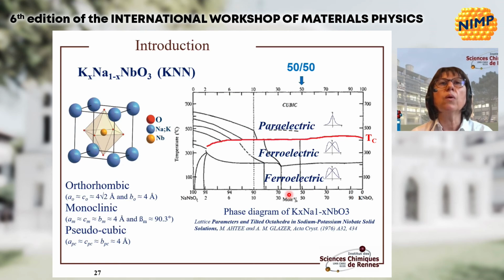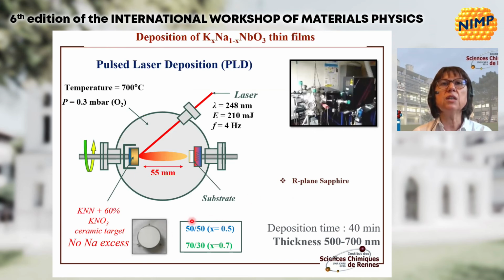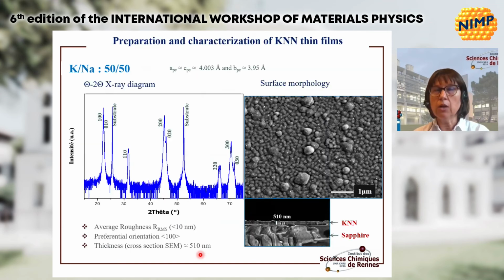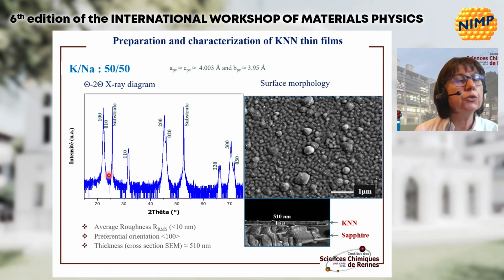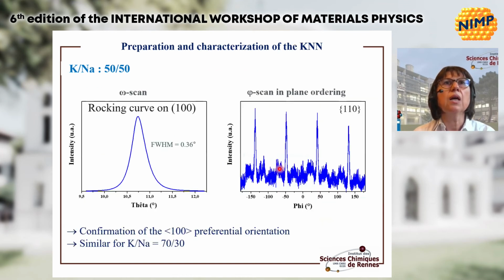So, we have already seen the phase diagram. The main composition we have studied is a 50-50 ratio between potassium and sodium, but we have also compared it to 70-30. Thin films have been deposited on R-plane sapphire. You can see here the theta-two-theta X-ray diffraction on sapphire, with a preferential orientation along the <100> direction. You can see here the classical morphology of such films. In this case, we have a texture, and the phi scan shows that there is some in-plane preferential orientation, but not a very beautiful epitaxy. We have similar results on the second composition.